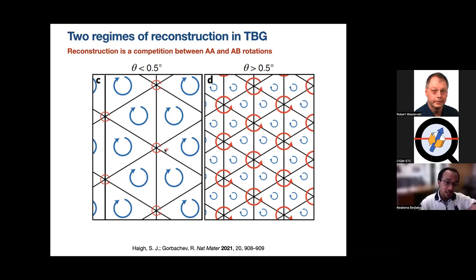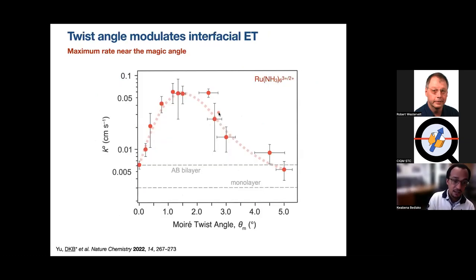And the one that wins out at lower angles is the AB counter rotation, which serves to make the bands more dispersive because it makes the material look more like Bernal stack bilayer graphene. Whereas the one that wins out at larger angles is the AA rotation, which makes the material look more overall like twisted bilayer graphene, if you will. And that actually serves to preserve the flat bands and isolate them from the more dispersive high energy bands. And so that actually is one of the reasons why you have flat bands being frustrated at lower angles and being preserved at higher angles. The relaxation process in a sense is actually beneficial to the flat bands at that first magic angle.